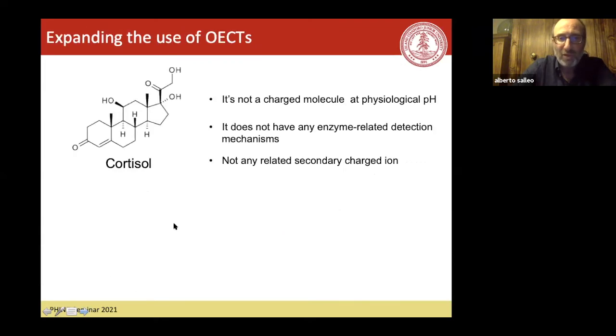So how do you measure cortisol if your sensor is really an ion sensor? Well, one way would be to see if there is any degradation reaction with an enzyme that would turn cortisol into something charged or would produce something charged as a byproduct. And we actually couldn't find any enzyme-related detection mechanism. Cortisol itself is not charged at physiological pH, and it's not related to any secondary charged ion. In fact, we didn't really like the idea of going with an enzyme anyway, because of the reasons that I told you. They degrade, especially for wearable systems, it's not ideal. And also they desorb. It's pretty hard to have them bound to something and maintain their functionality in a reproducible way.